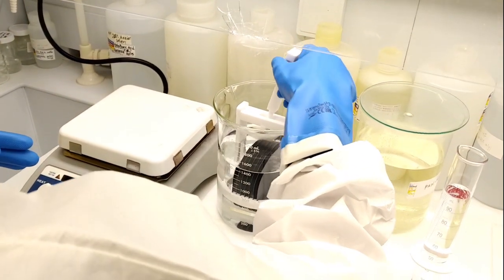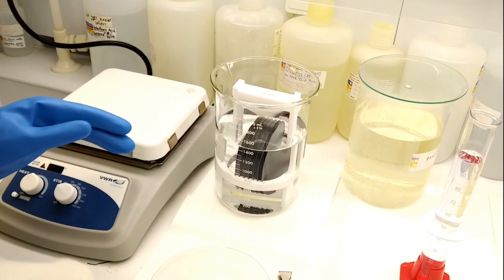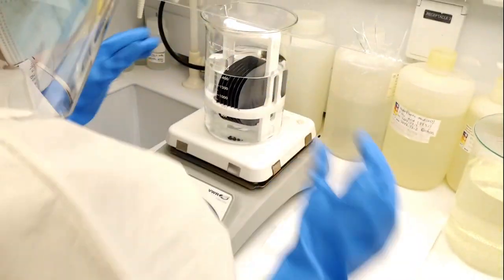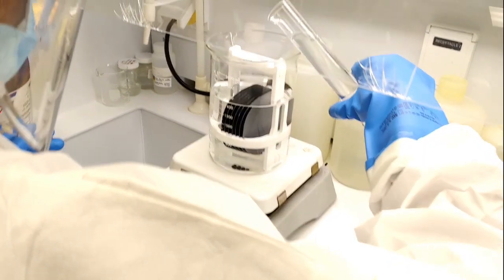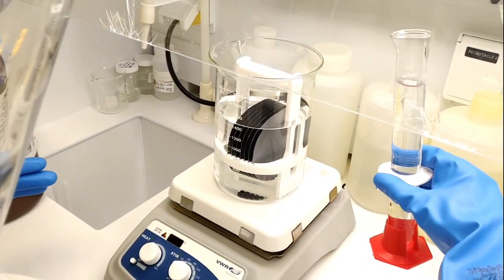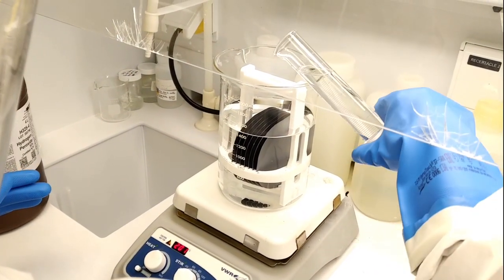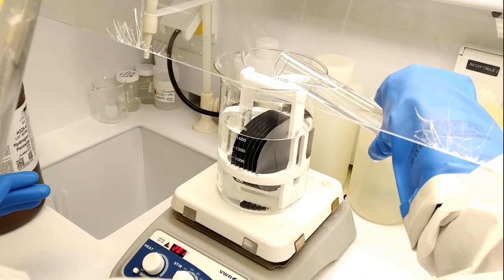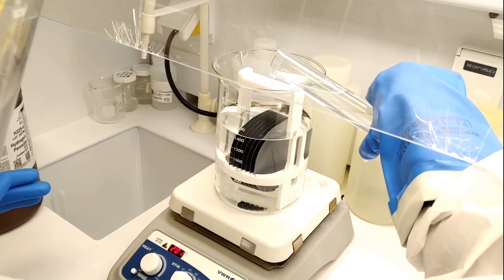Before growing the silicon oxide, the silicon wafers need to be cleaned. The first step in every thermal process of the wafer is an RCA clean to remove contamination before it can be baked into the wafer. Here, your lab instructor Bahare is cleaning the wafers in a heated RCA solution. Hydrogen peroxide is then added to the solution.